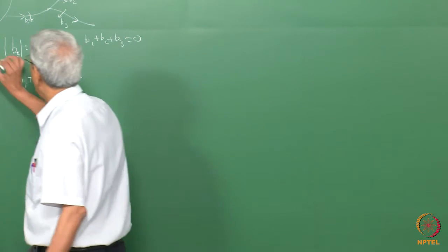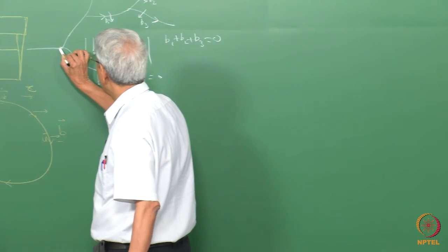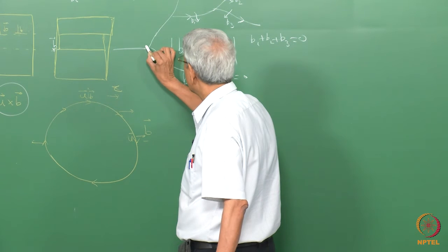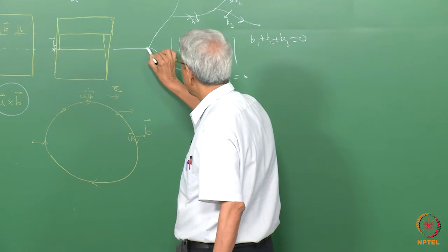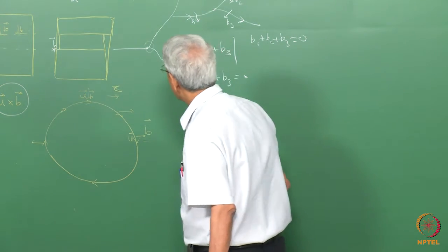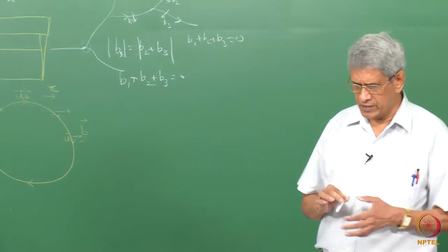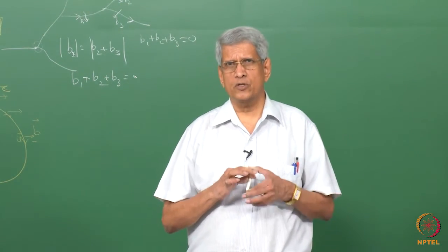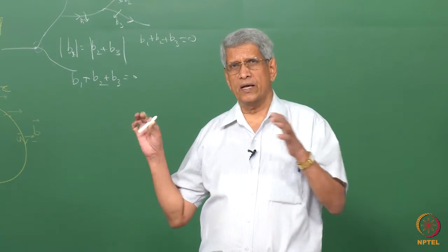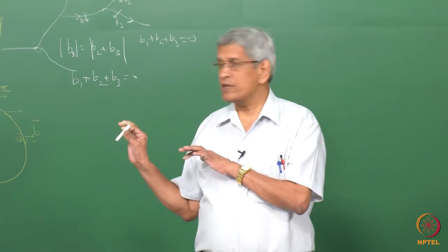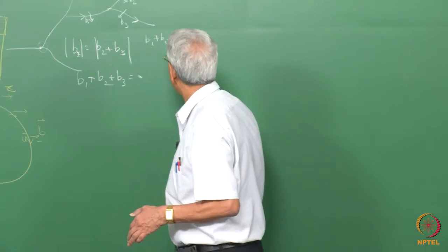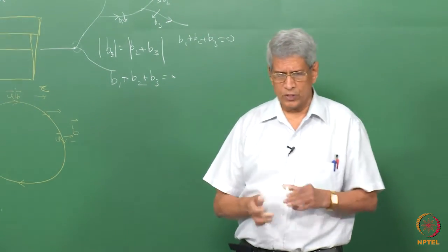And many dislocations are there. We will find that if a dislocation has to terminate, another dislocation will originate from this point. So, these sorts of junctions will be formed. What is the condition for these junctions to be formed? It is that the sum of the Burgers vectors has to be equal to 0.